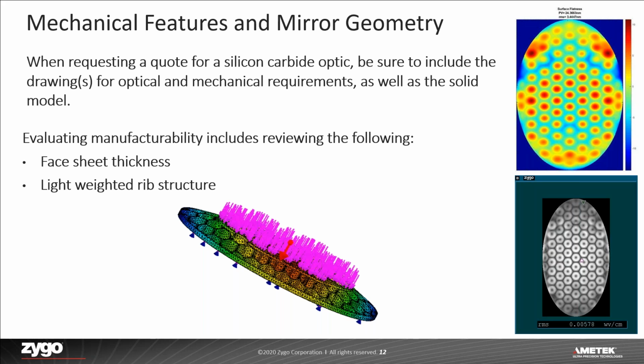Now, when we talk about mechanical features and mirror geometry, when requesting a quote from Zygo, please be sure to include your drawings for optical and mechanical requirements, but also the solid model up front. That's going to really help us evaluate the manufacturability when we're reviewing the RFQ. In regards to the face sheet, face sheet thickness is always something we want to take a look at. Designers want to keep that face sheet as thin as possible in order to keep the mirror as light as possible. But there is that fine line because a very thin face sheet can cause lightweighting ribs from the backside to print through to the optical surface.